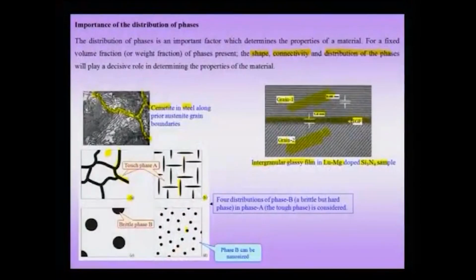But you can clearly see in the example B that the phase B is in the form of a needle or a lens, or what you might call a highly oblate spheroid in 3 dimensions. This kind of a morphology would mean that at the tip of these precipitates, which I am marking here in yellow, there will be actually high stress concentration. So, let me draw that here.